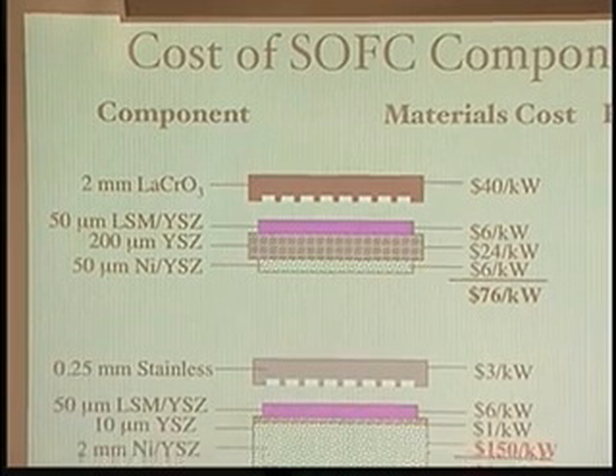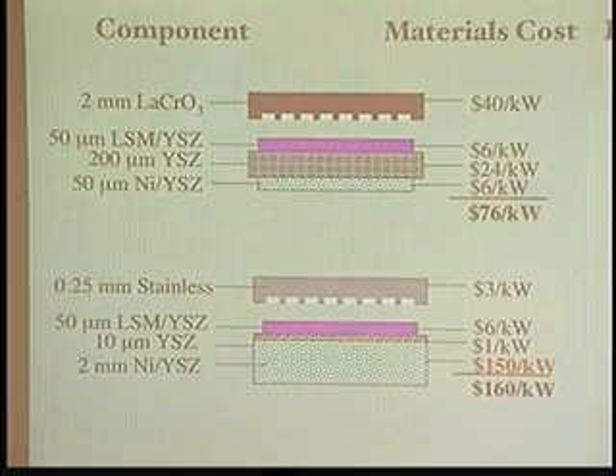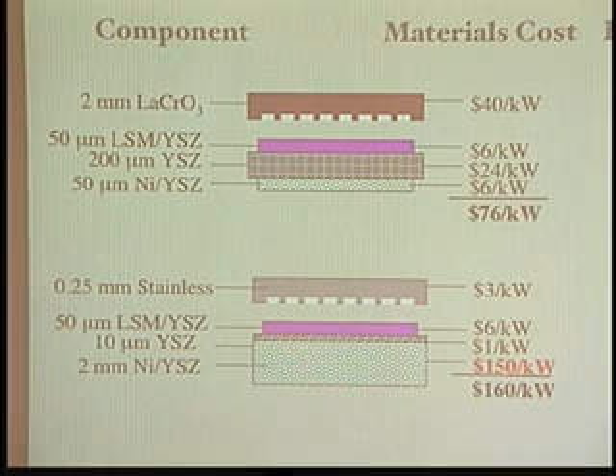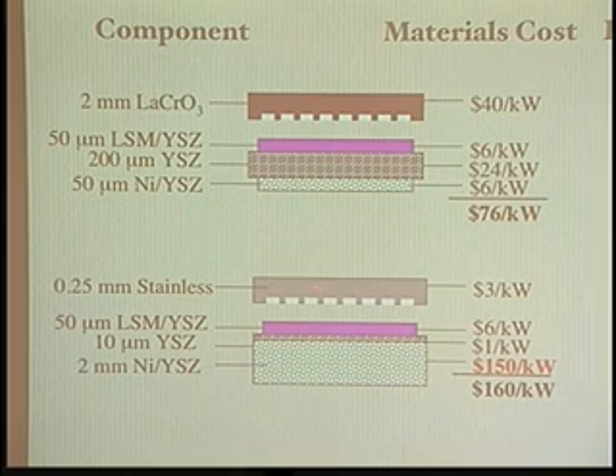Now, here's the anode-supported cell. This is what we were doing here at LBL. Now we have a large anode and a very thin electrolyte. And then you can screen print this. Now you can use stainless steel instead of this ceramic, because the temperature is low enough to do that. This is not going to get severely corroded at these temperatures.